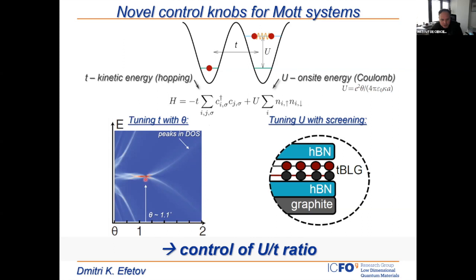So on magic angle, T is of course the lowest. T has a minimum. But whenever we go slightly away from the magic angle, T becomes much bigger. So the bandwidth of a 1.2 degree twisted bilayer graphene device is already 10 times bigger. So it's already more like 100 meV. So we can really accurately control T by just slightly changing the twist angle, but also we can really control